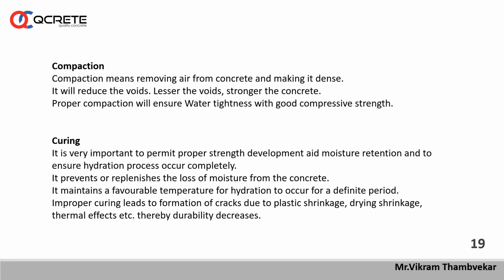Because I have seen, because of wrong application at site, many problems have arisen for the structures. And of course, curing is also a very important factor. All project people should use only potable water, or if other well water or bore water is there, its pH and other parameters like chloride content, sulfate content, and so many things, which are laid down in IS 456, should be checked properly, and then only water can be used to make fresh concrete or for curing also.